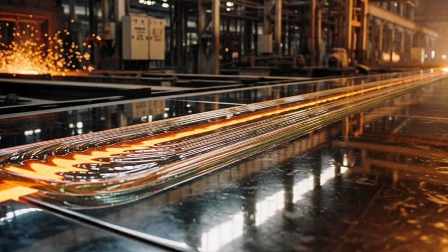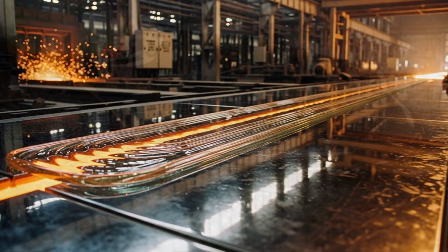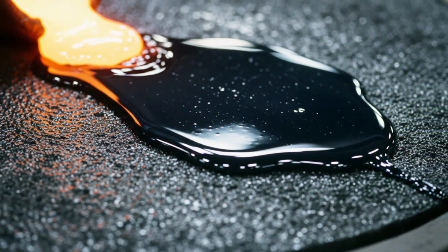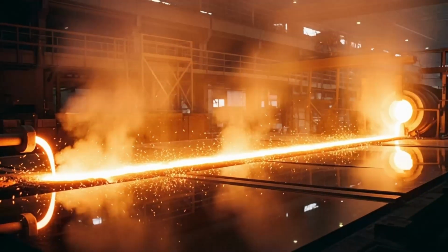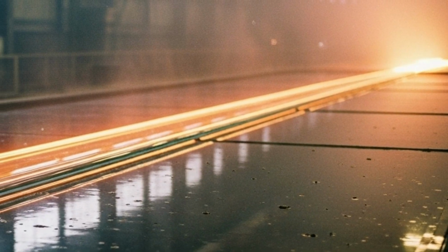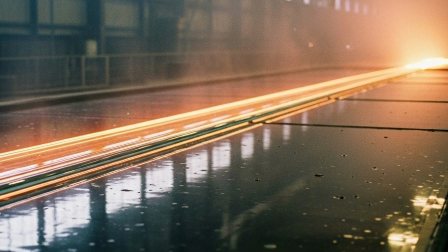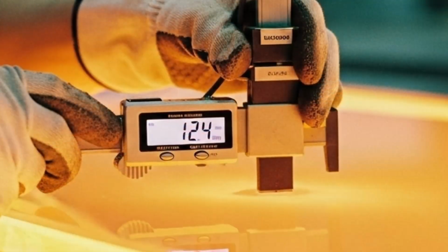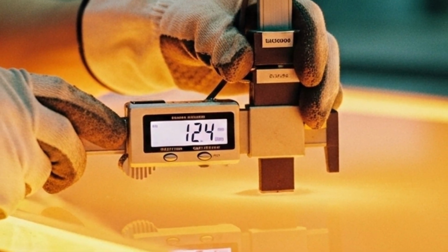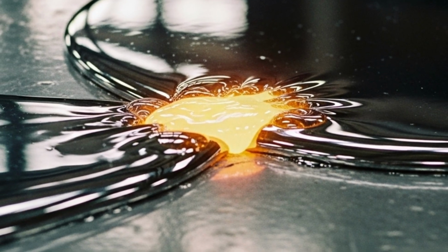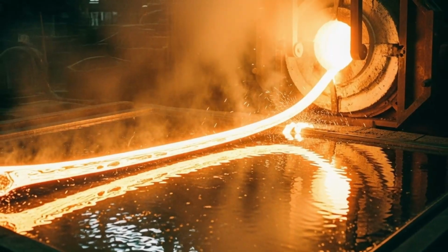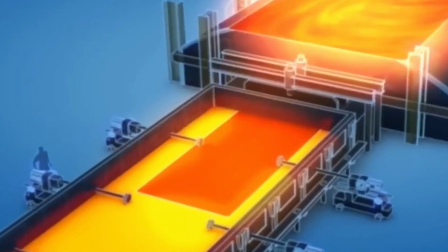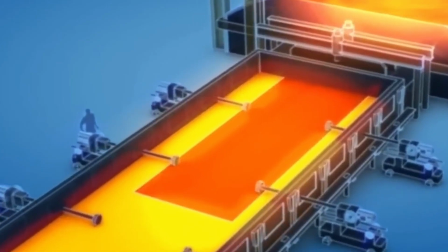The float process is used, where molten glass is poured onto a bath of liquid tin at around 1000 degrees Celsius. Thanks to the difference in density, the glass floats on the tin and spreads into a continuous sheet, perfectly level, with a thickness ranging from 3 to 19 millimeters. The surface of the tin, pure at 100%, acts as an invisible mold, giving the glass a perfectly smooth and uniform face. This eliminates the need for later polishing, a breakthrough that revolutionized the industry in the mid-20th century.